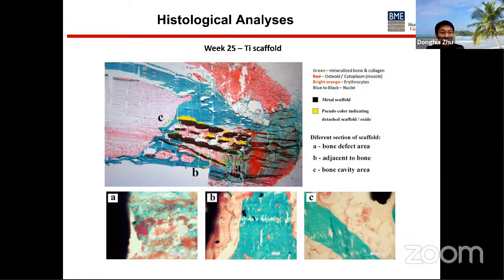Only some mixture of mineralized bone and osteoid in the defect region were observed, with less mineralized bone inside the scaffold. Relatively thick mineralization is observed in the cavity region; however, no aggregation of different blood cells was observed, indicating less vascularization for the titanium case.